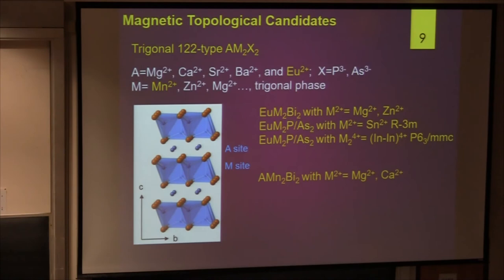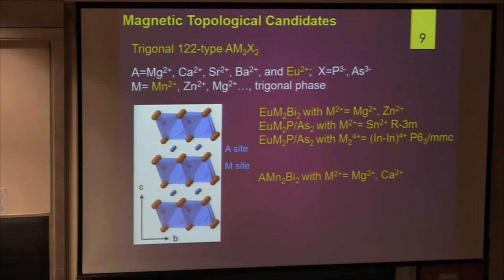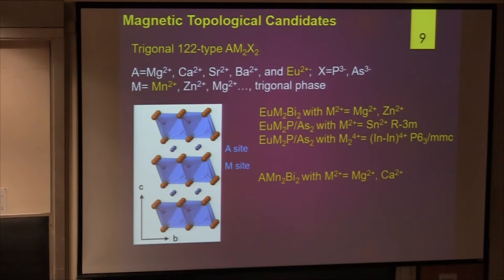As a chemist, if we need to put magnetism into the system, what can we do? We have an A-site, which is the magnesium site. We also have a bismuth site and a magnesium site. We don't want to replace the bismuth because bismuth gives good spin-orbit coupling. What we can do is replace the magnesium using europium — europium is magnetic. Also, this magnesium can be replaced by manganese, which is also magnetic. We can keep playing the charge-balance game and get many, many materials with interesting properties.